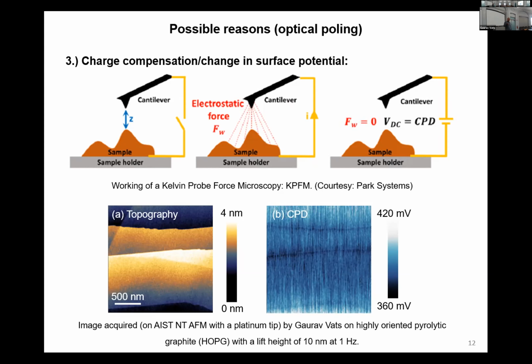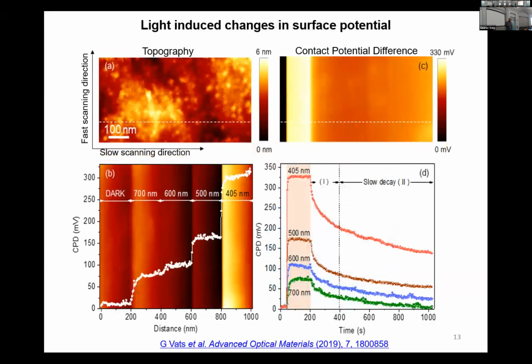Now let's see what I got with this technique. So this is the surface of my material. I was scanning like this. So you can see this is the fast scanning direction. This is the slow scanning direction. At the same time, I was acquiring this contact potential difference. So again, this direction. So in this figure C, what I did is I started the measurement in dark. No light was shining on the sample. And at this point, where you see the yellow color appears, I exposed it to light while performing the measurement. And you can see the color changes. This contrast means the potential is higher. And at this point, I turn the laser off and let it relax.